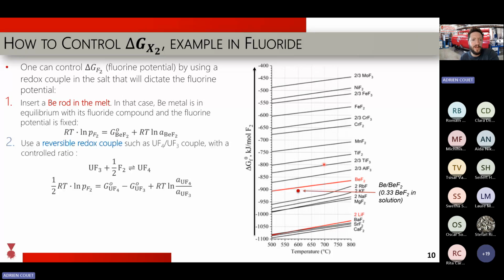So another way that people have found for many years now is that we are putting fuel in our salt, so we have uranium. Why don't we play on this amphoteric approach of uranium, where you have different oxidation states of elements like UF3, UF4, and if you control this ratio, then you control the partial pressure of fluorine. So that seems a very powerful means to actually control partial pressure.